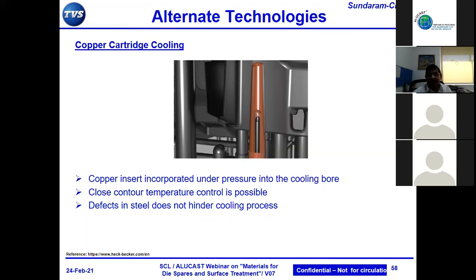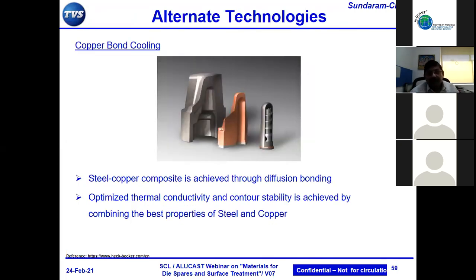And you have a jet cooling, which actually almost goes to the surface of the steel, the copper. So even though there's a cracking on the steel's insert surface, there's no water leakage. So these are some of the things which are quite innovative, and people have been incorporating in some of their designs with multi-material, multi-process design. That is a dissection of that particular assembly. So you have the contour of the copper, which has gone exactly into this kind of insert. And in fact, it can go as close to the surface as possible.